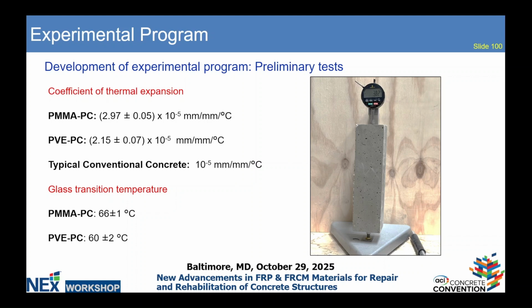For reference, regular concrete has a coefficient of thermal expansion of 1 × 10^-5 millimeter per degree Celsius, which means polymer concrete has a coefficient of thermal expansion of 2 to 3 times the regular concrete.